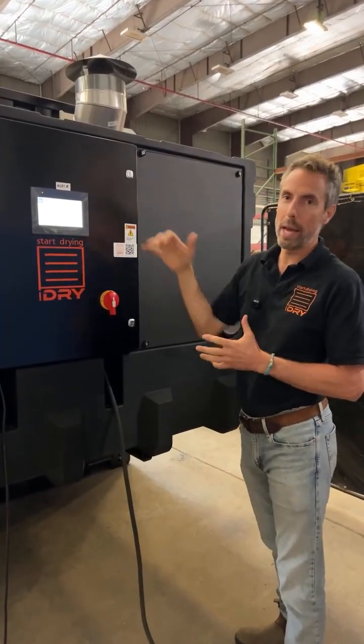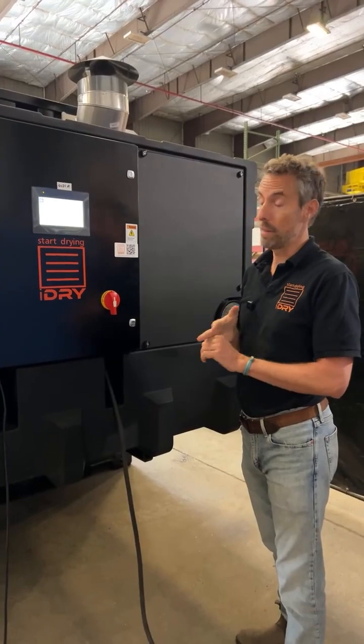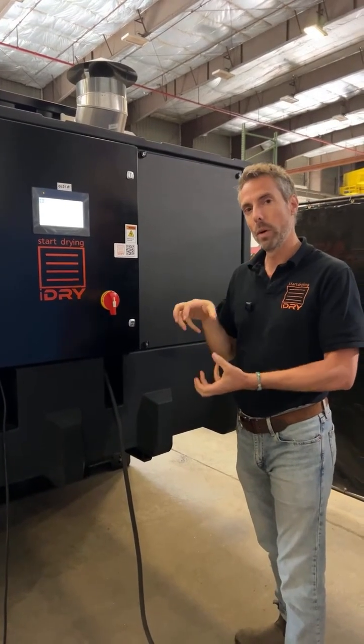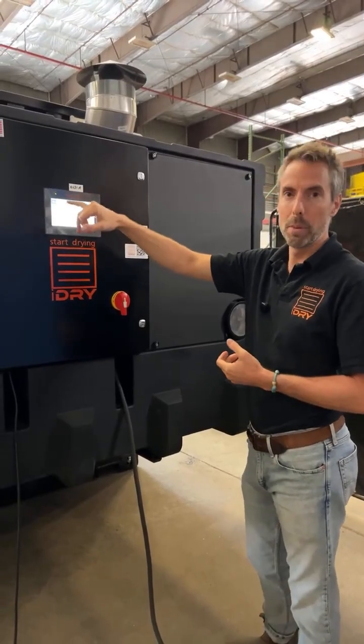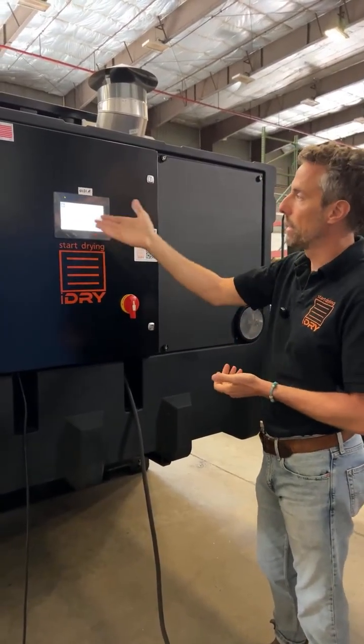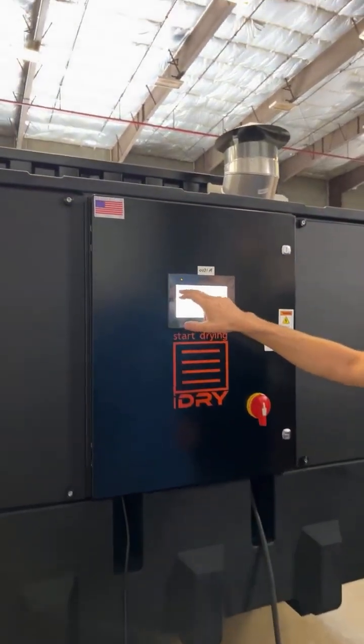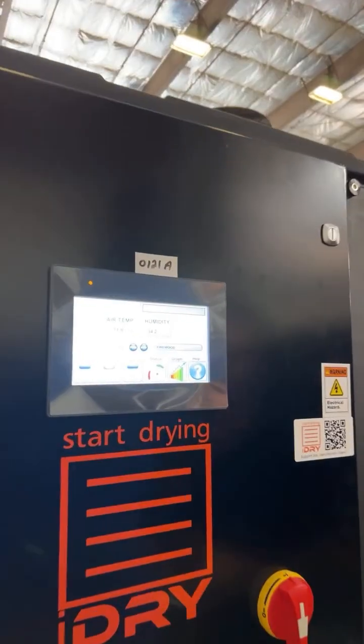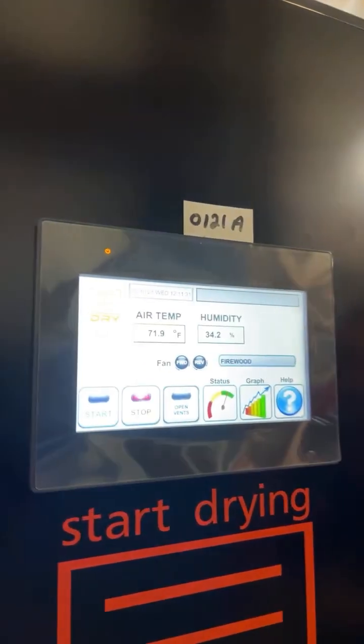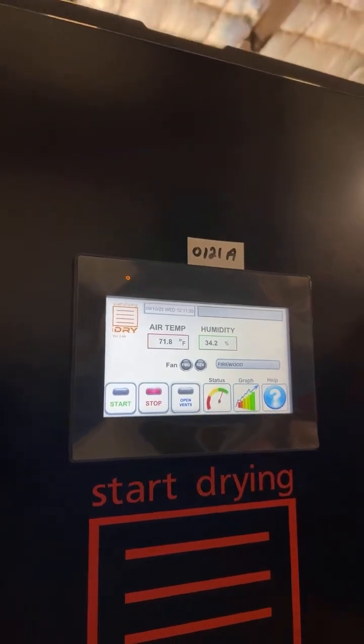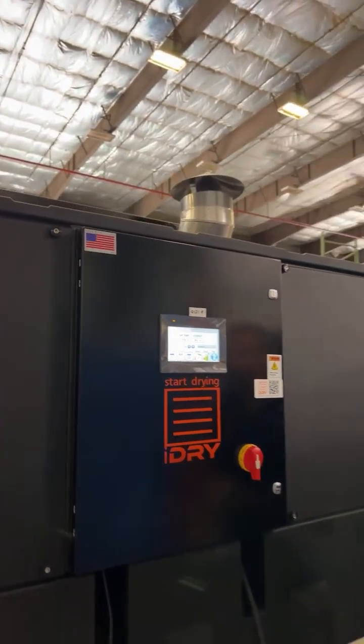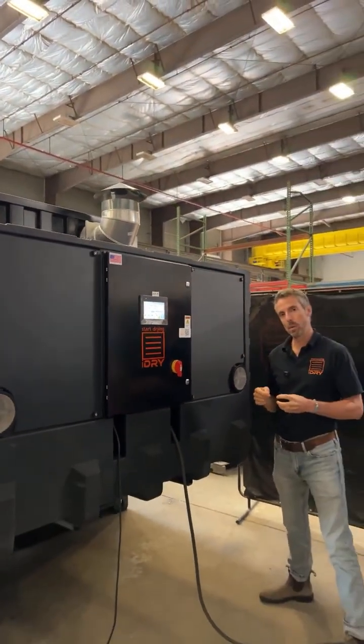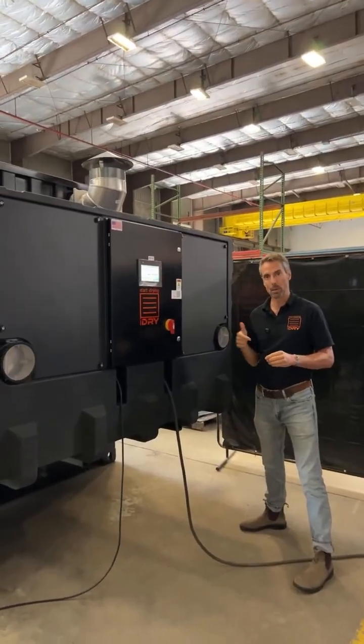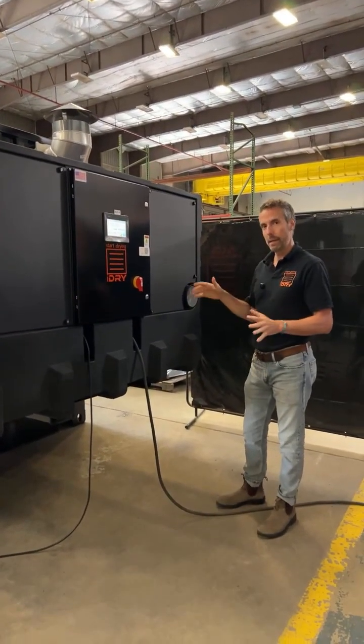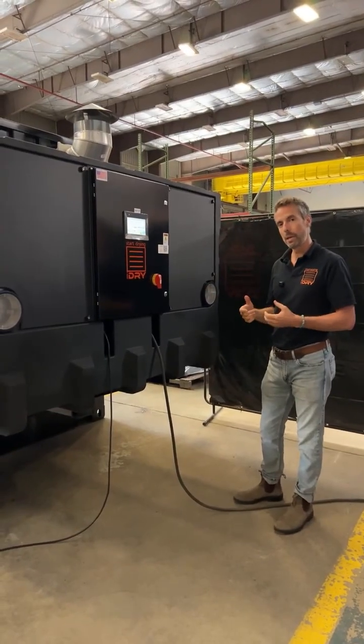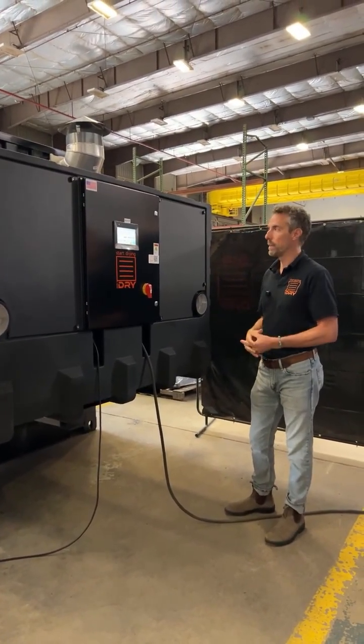Usually people for firewood are drying even hotter than that. But you really won't have properly dry and disinfected firewood until we get the core of that wood up to 140 degrees, which means getting the kiln temperature above 160. You can see that all here. We have proof that it reached that. We have a kiln report if you need that. And if you're drying firewood and moving it across county lines or state lines, where an inspector wants to see that you have achieved that 140 degree core temperature, we also sell wireless wood core probes. You just drill a hole in a piece of cordwood, throw it in the kiln, start it up, and it goes for the ride and collects that temperature data, so you can tell them for sure that inside this cordwood we reached the required temperatures.